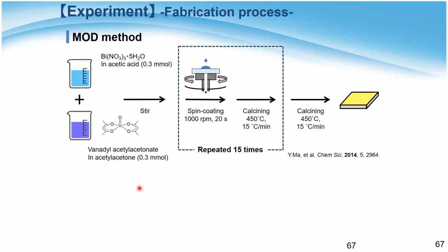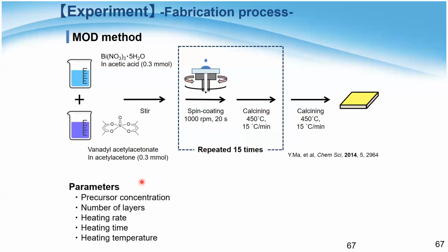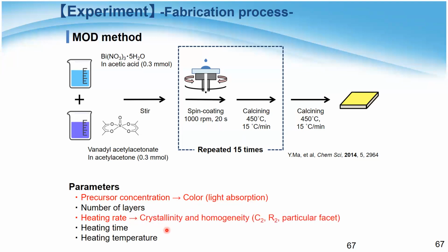It's the second part. So there are many experimental parameters such as precursor concentration, number of layers, heating rate, heating time, and temperature. We focused on the precursor concentration and heating rate because concentration obviously gives a color change from our experience, and heating rate usually changes the crystallinity and homogeneity. So the R2 or particular facet can be modified by these experimental conditions. So we changed the concentration and heating rate.